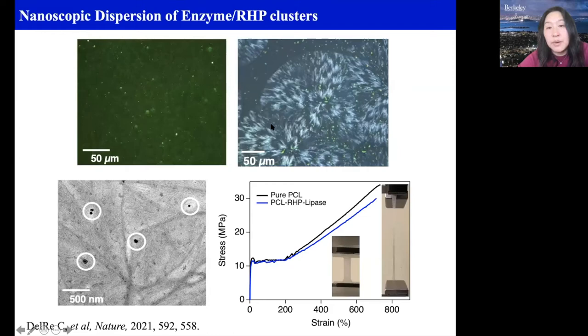But the most important part is that when you overlay it with the polarized optical microscope, you basically see the spherulite, and that's where the crystalline domain is. You also see the amorphous region. So the enzymes are pretty homogeneously distributed across, rather than just in a particular area. We want it to be homogeneous because we really don't want microplastic that can linger around. And if you look at the transmission electron microscope, you can see there are enzyme clusters. We believe there are smaller enzyme clusters inside the amorphous region that we are not able to see with TEM.